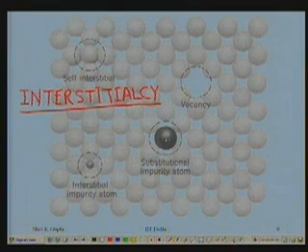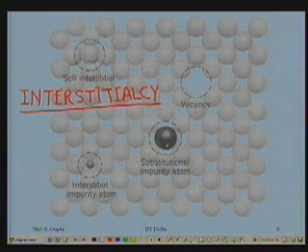But this kind of defect is quite possible, the substitutional impurity atom, which we shall see in semiconductors like silicon, where I dope it with phosphorus, or I dope it with boron, I dope it with gallium and things like that. So this doping which I do will be a substitutional impurity atom. sp3 bonds are still satisfied. What is going to be affected is the number of electrons around this atom, which may not be 4; it may be 3 or it may be 5 or it may be 6. That depends upon what impurity I am adding, but 4 bonds can still be formed.